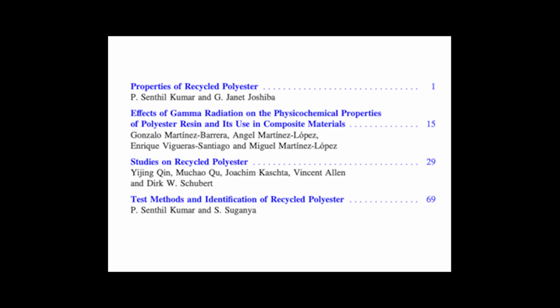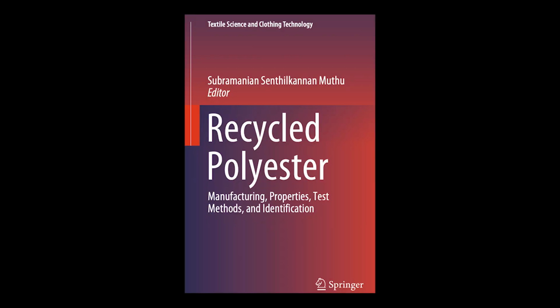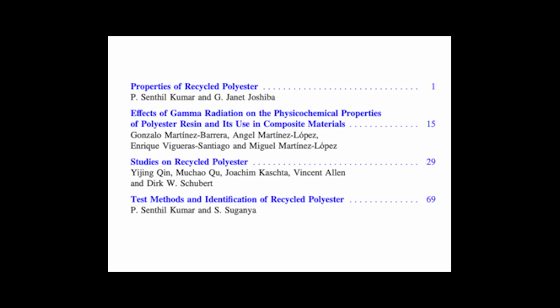Okay, so rPETB is strong due to orientation. What about the virgin vPET1 it was compared to? How did it get its strength? The vPET1 achieved its comparable strength via a more balanced combination. Yeah. It had decent molecular orientation. Its shrinkage ratio was lower, 39.3%. Right. But it had significantly higher crystallinity. Xc measured at 17.2%. So the recycled stuff was strong because it was pulled taut and aligned, while the virgin stuff was strong because it was inherently more organized and packed internally.